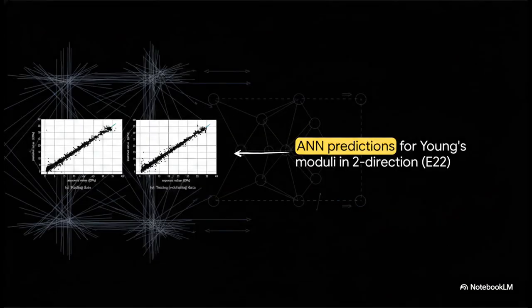Next up, Figure 11 analyzes the Young's modulus in the transverse 2 direction, or E22. And once again, the predictions just align beautifully with the expected computational results without any sort of excessive scattering. This really confirms that the model handles the complex, multidirectional elastic tensors of the composite material. And honestly, this is a fact that's further validated in the paper by Figure 12, which flawlessly predicts the in-plane shear moduli too. It's hitting the nail on the head across the board.